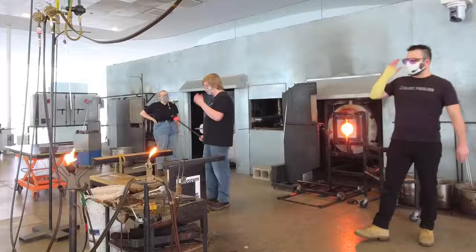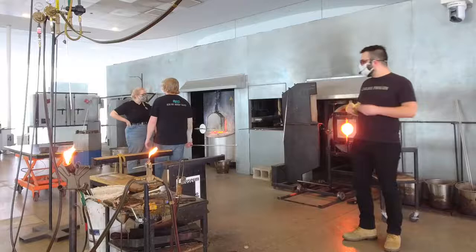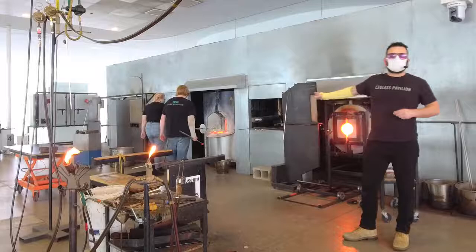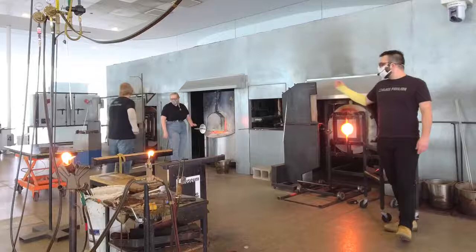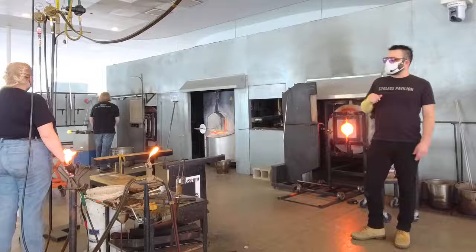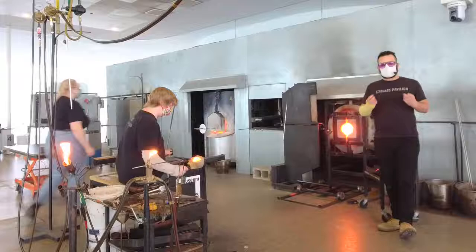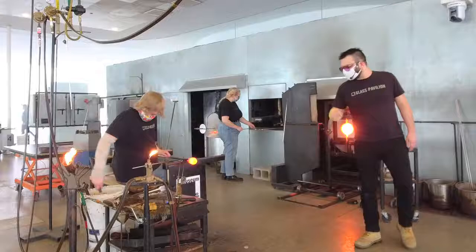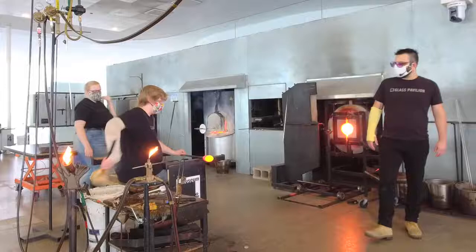Colin is going to wait a little while. The main reason is because if he introduced that into our furnace and that color gets too hot, some of that color might get a little too melty, slip off, and fall into our furnace — which would be a big problem. But he waited long enough where he felt confident in it. Sticking it in, rotating, and then pulling out a huge blob of glass. He's going to come over to his bench and use one of our favorite tools, which is called the block. It is carved out of a block of cherry wood — any kind of fruit wood would work very well for this. Anything that's high in water saturation and very, very low in sap content. As long as Colin keeps turning, that wood will never be burnt out. Creates a nice little layer — you can see the steam coming off.